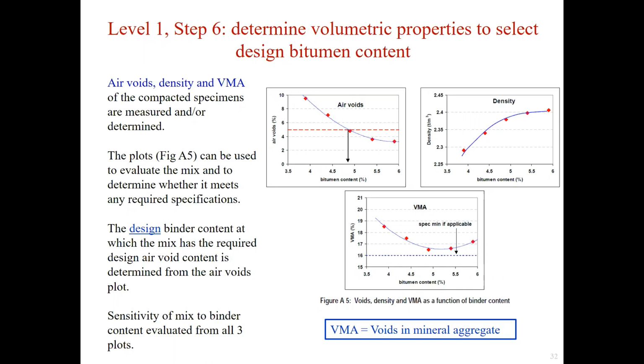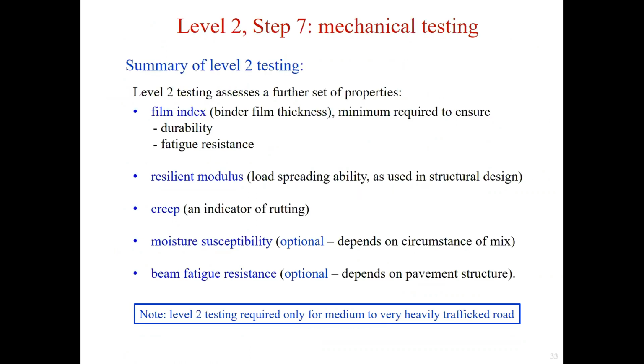For example, if an air void of 5% is required, then according to the first figure, the design bitumen content is chosen as 4.8%. We could also check the sensitivity of the asphalt mix parameters to binder content from these figures. For example, if the bitumen content was increased from 4.5% to 5%, how do the air voids, density, and VMA change accordingly.